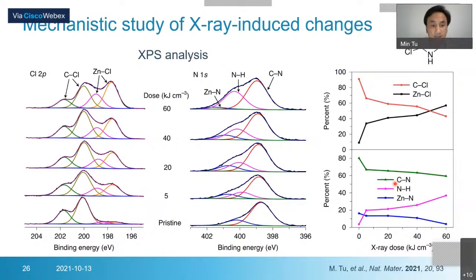And we also did some XPS analysis. If you look at chlorine, the pristine one only has carbon chlorine. Then with the increase of the X-ray exposure, we see a lot of zinc chloride formation, which supports our hypothesis. So the X-ray induces the formation of chlorine radicals, and it cleaves the imidazole ring and induces other reactions. Also, it forms zinc chloride, and it cleaves the zinc nitrogen bond. So this is what we understand so far from this kind of mechanistic study, but still we cannot resolve all the reactions in this complicated system.